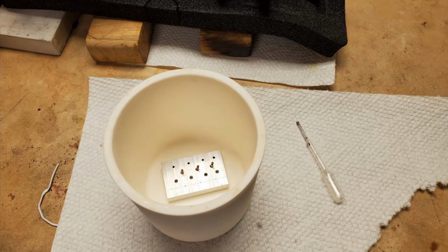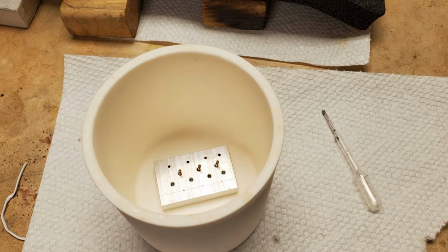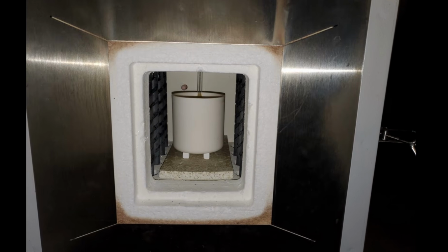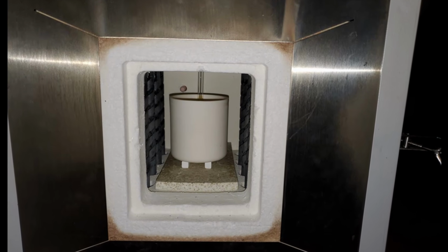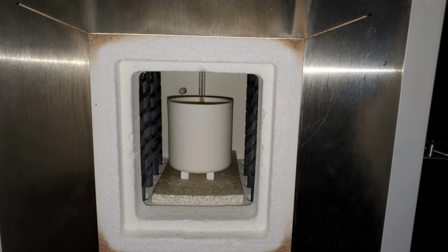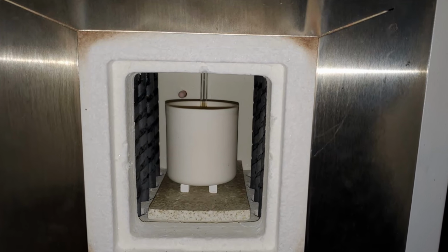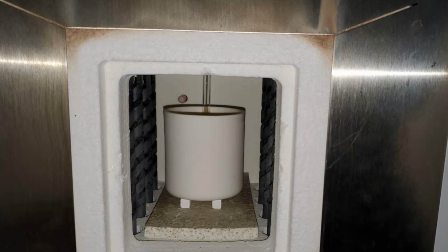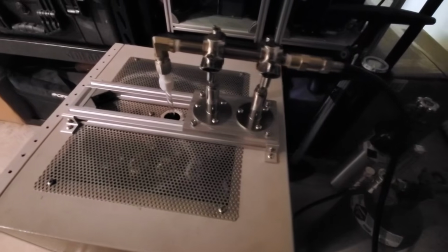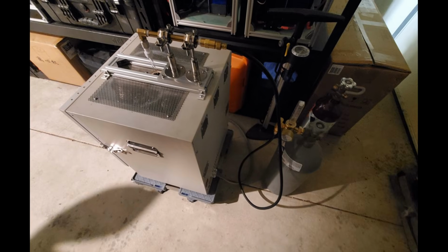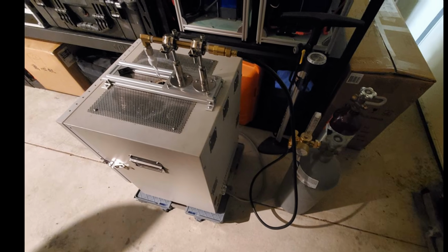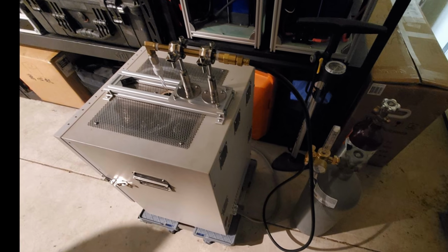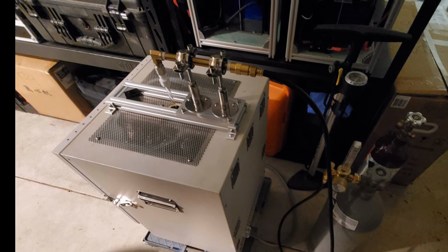Finally, the metal electrodes are baked at around 300 degrees Celsius to sinter the nanoparticles. For silver electrodes, this baking step can be done in air, while for copper electrodes, it has to be done in argon. Here's the poor man's argon flow system for my furnace. I also tried tungsten electrodes, yet those showed very poor adhesion with silver nanoparticles. I have since just used pure silver for the electrodes.